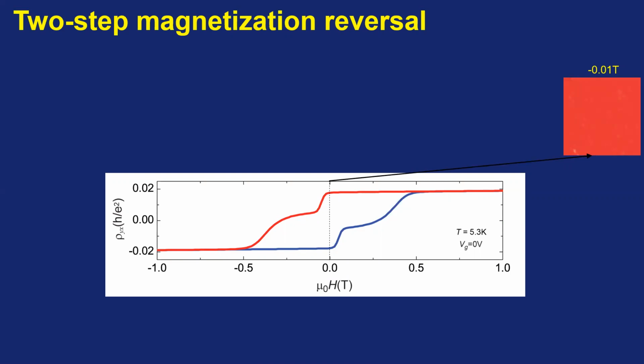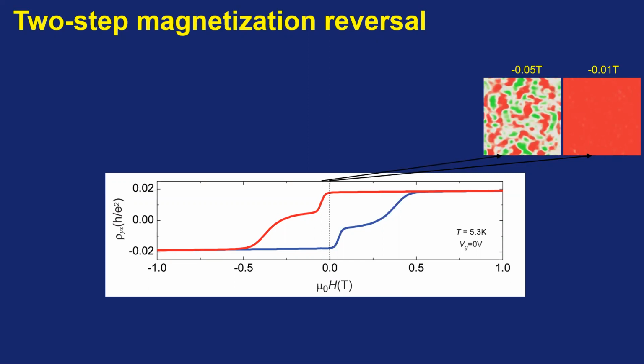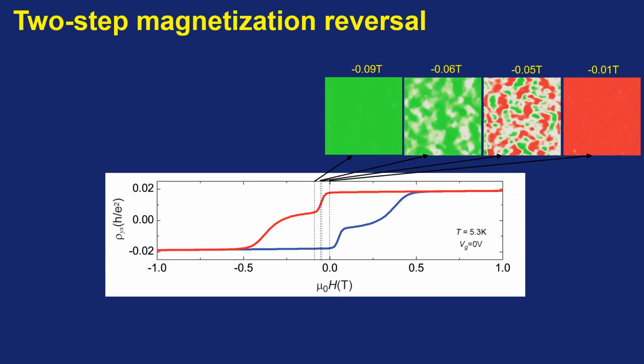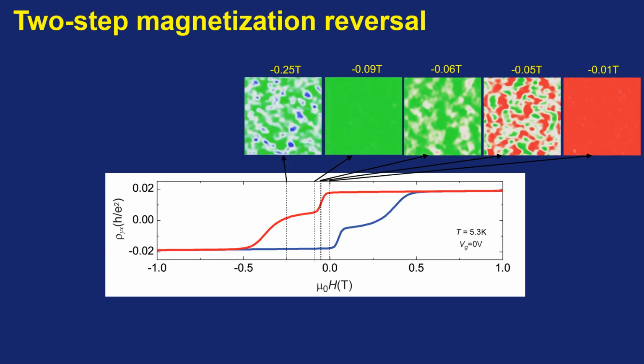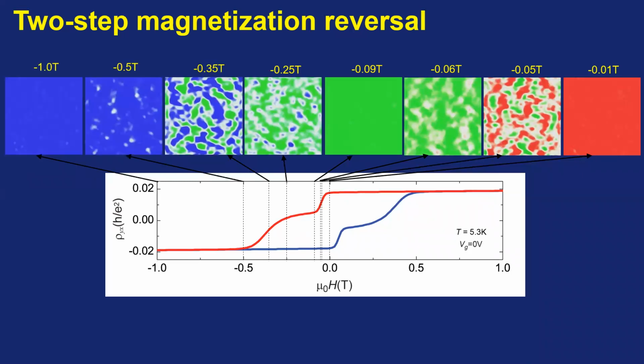In this transport result, we indeed see the two-step magnetization transition. We first apply 1.5 Tesla to the sample and sweep the magnetic field back to the negative side. At minus 0.01 Tesla, we can see a uniform red color, which means the top vanadium layer and bottom chromium layer have parallel magnetization. When we further sweep the magnetic field to the negative side, we can see some green domains form. And at about minus 0.09 Tesla, it shows uniform green color. If we further increase the magnetic field, some blue color domains form, and at minus 1 Tesla, it shows uniform blue color. This means the downward parallel magnetization.